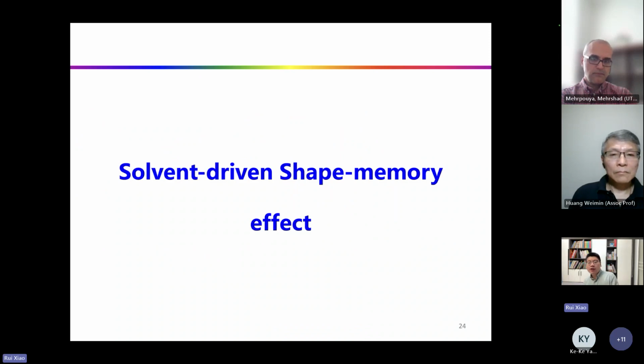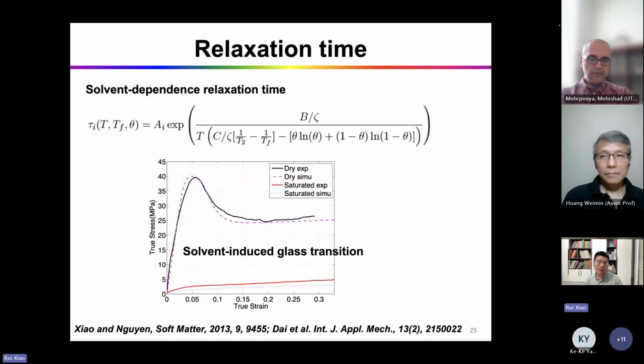So for the solvent-driven shape memory effect, you need to model two things. The first thing is you need to model how the solvent affects the glass transition - basically, the introduced solvent can reduce the viscosity. So you have to define an explicit function of the viscosity dependence on solvent concentration. The more solvent, the softer the material is.